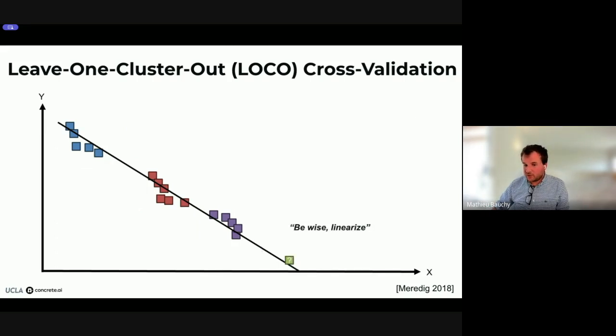And so, in general, those models, of course, they are still based on neural networks, so they are not fully linear, but they tend to be more linear. And that's basically because a linear function is kind of the only function that really can extrapolate reasonably well outside the range that it is trained on. So again, those models are not linear. They are still based on neural networks, but they tend to give more linear extrapolation. And we found this to be the most efficient to discover new materials that are different from the ones in the training set.